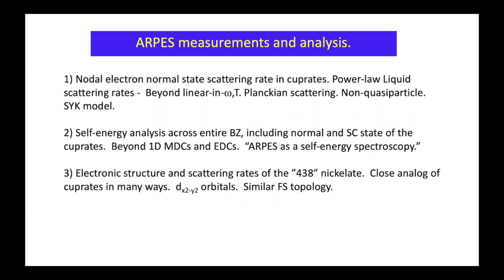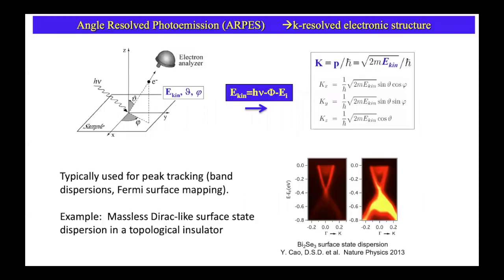And then I'll talk about these nickelates. We call them the 4-3-8 tri-layer. There are three nickel layers here, and these are very close analogs to the cuprates. The same dx²-y² orbitals, similar Fermi surface topology. We don't seem to have this extra 3D electron pocket in these, but they haven't been taken superconducting yet. It's very hard to dope them away. They're basically line compounds.